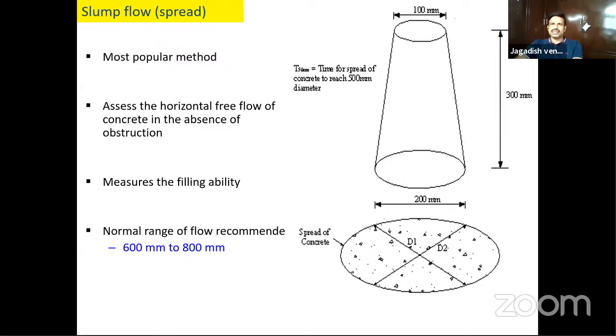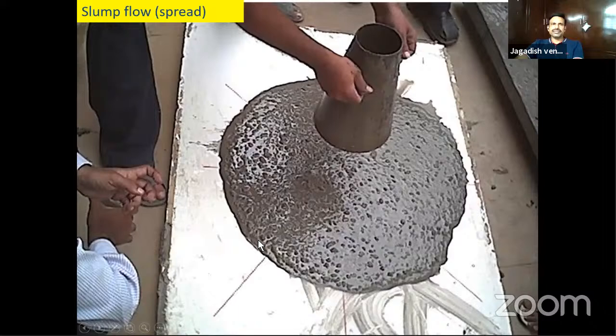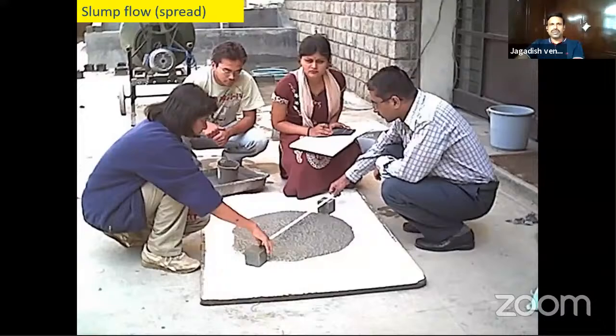Normally for normal concrete, you place the concrete in 3 layers, tamp each layer 25 times, and then you lift the slump cone. You measure the vertical slump in case of normal concrete. But in case of self-compacting concrete, because it flows, you have to measure the horizontal spread. So once you lift the slump cone, it spreads, and you have to measure the horizontal free flow. The range of the spread should be between 600 to 800 mm. So once you lift, the concrete flows. This is how you measure.